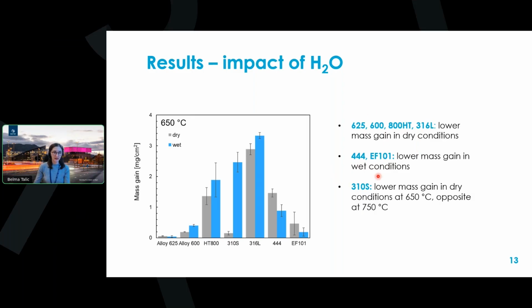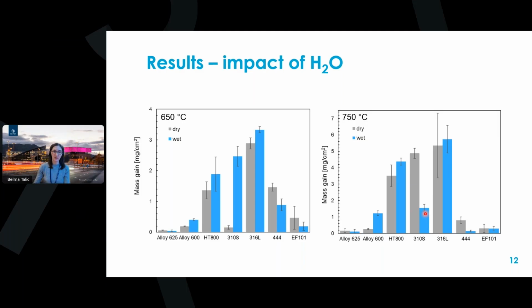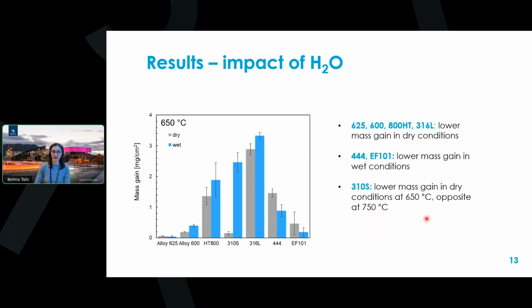So I said that for most of the alloys, this was the same at the two temperatures. The only exception is the 310S, which had at 650 shown here, lowest mass gain in dry conditions, while at 750 we had the lowest mass gain at the wet conditions.